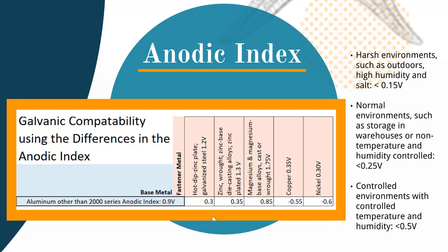There are three categories of environments to consider: harsh, normal, and controlled. If you want absolutely no galvanic corrosion, the values above show that harsh needs to be less than 0.15 volts, normal needs to be less than 0.25 volts, and controlled needs to be less than 0.5 volts. This means that only under a controlled environment will there be no galvanic corrosion. However, we are not normally under controlled environments, so the closest values to achieving the least amount of galvanic corrosion will be with either zinc or galvanized steel at 0.3 volts.